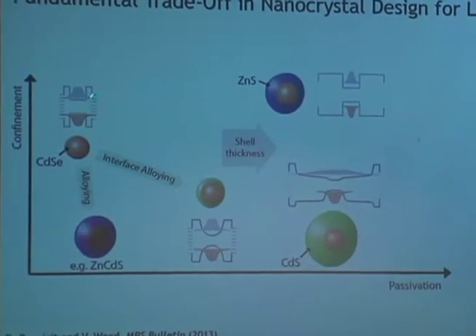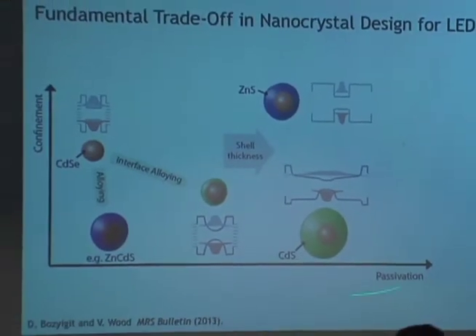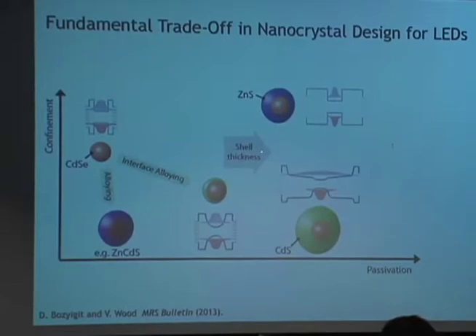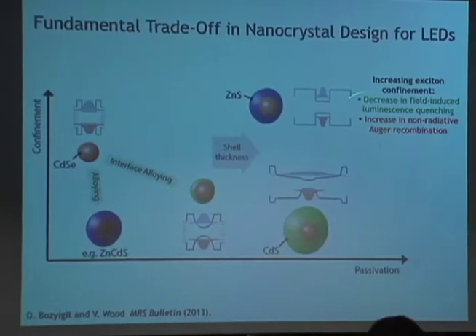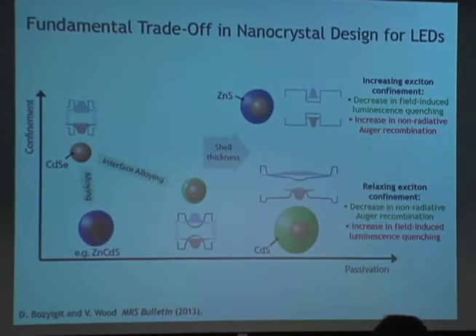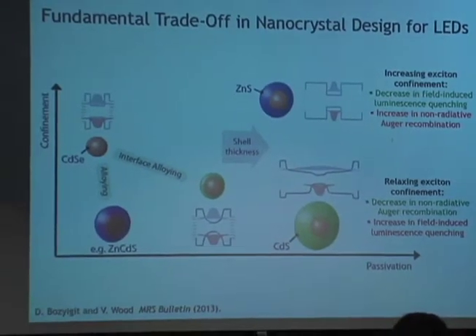So what this means is that if we look at what we can do synthetically in terms of quantum dots to date, with LED applications in mind, we always want to passivate the surface of our quantum dot. We don't want to just have a core, because there you have a lot of trap states, which lead to high non-radiative recombination. So you always want to passivate your quantum dot with a shell. And so you have two options. Either you choose a shell with a wide band gap that tightly confines your wave functions, or one that doesn't tightly confine them. This configuration is very good, as we just saw, for luminescence quenching, but it has high Auger. And if you now relax your exciton confinement, this is great for decreasing Auger, but now we saw that it's also bad for this field-induced luminescence quenching.